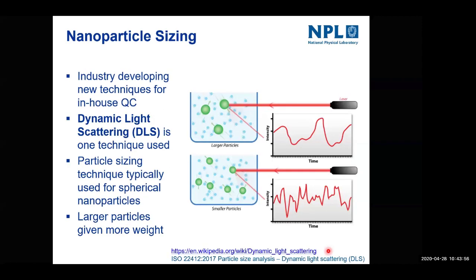Now, if I just bring the example of DLS, which is dynamic light scattering, it's well understood that techniques such as DLS and other nanoparticle sizing techniques are essentially modeled on using spherical nanoparticles. They're not there to really, or at least yet, understand non-spherical particles accurately, or quantify that. And also they tend to give larger particles more weight. So if you've got, as you saw at the beginning, this SEM distribution of lateral size, actually with a nanoparticle sizing technique, because of the way they fundamentally work with light scattering, you see more of a skew towards the larger sizes. So that can therefore give you spurious results. If you take a technique such as DLS, you can end up having a wrong result if you take it quantitatively.